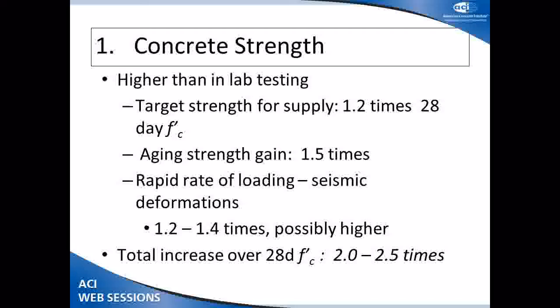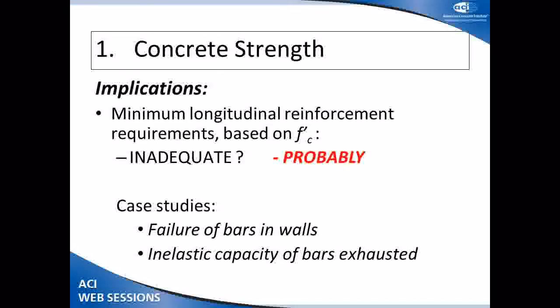You'll find that under dynamic loading, the concrete, particularly the tensile capacity, can be 1.2 to 1.4 times larger. That means that the compressive strength can be anything from 2 to 2.5 times. The implications are: are the minimum longitudinal requirements in our standards sufficient for the real crete as against the lab crete that we're dealing with in our labs and the equations are quantified against?